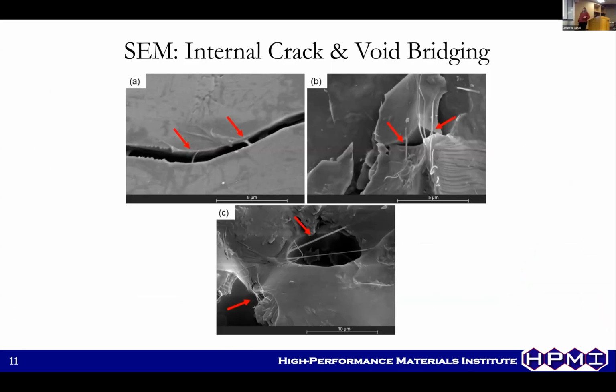You can see these are the 0.1% weight BNNT. So clearly with a one-shot burnout ceramic, you're going to have porosity. Even with these porous structures, you have BNNT bridging across the pores, which is why we have those increases in properties.